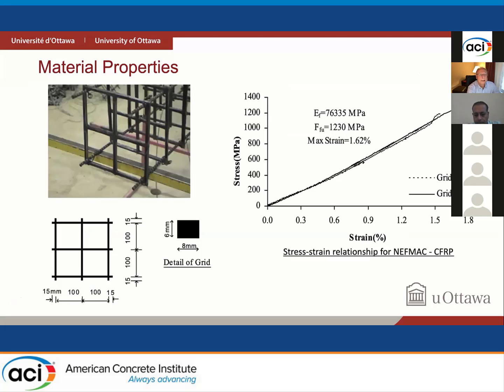In terms of transverse reinforcement, we use NEFMAC grids. These grids have had square or rectangular cross-section, 6 millimeters by 8 millimeters. And then we either had 4-cell grids or 6-cell grids. And we then used either 8-bar arrangements or 12-bar longitudinal bar arrangements with the dimensions that you see on the slide. The stress-strain relationship of NEFMAC CFRP reinforcement went all the way up to 1200 MPa.